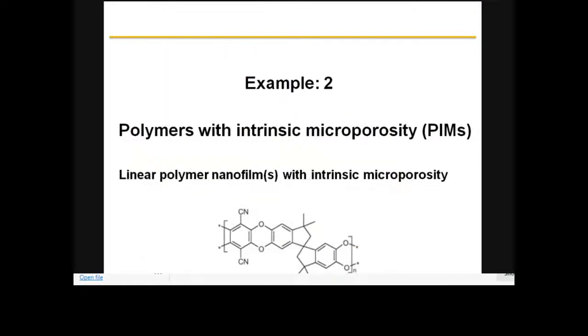Next example: the next thought was, if we can make a carbon thin film with a pore size less than 1 nanometer, can we make it from a polymer which has intrinsic microporosity? That means we choose a polymer that itself has a microporous structure. If we make a thin film, that microporous structure will be useful to make a membrane and use that structure to get separation. To do that, we started with PIM, polymer with intrinsic microporosity.